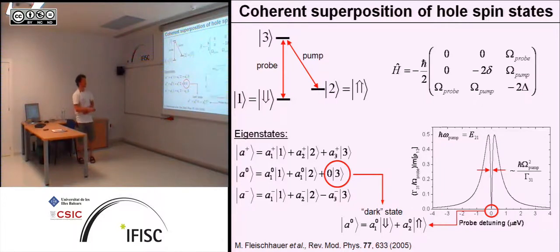And this now leads to this optical spectra. So here you would see the normal Lorentzian absorption, but in the middle here, suddenly you get a very dramatic and sharp dip. At zero detuning from the probe laser, from this transition, you suddenly see zero absorption. And that is because all the population is trapped inside this state and cannot couple to the excited level anymore, and that's why it's called coherent population trapping.